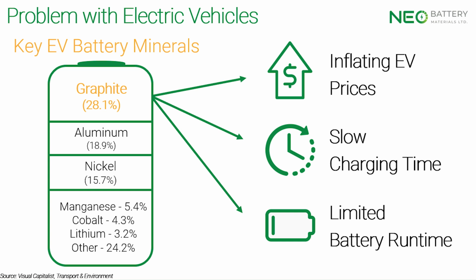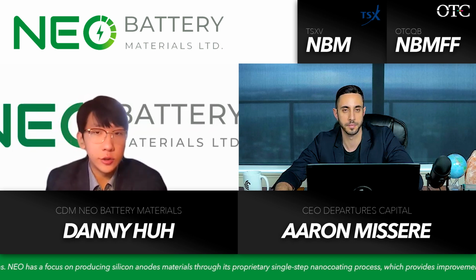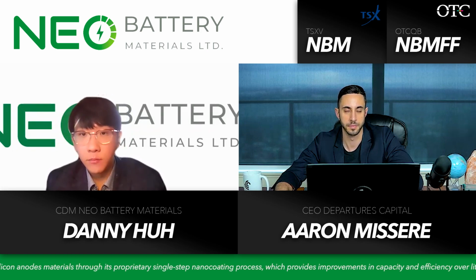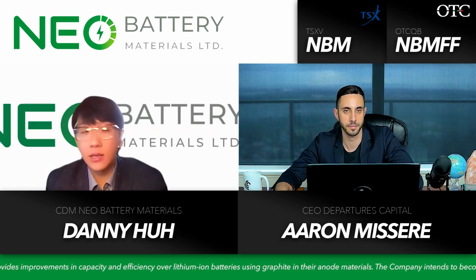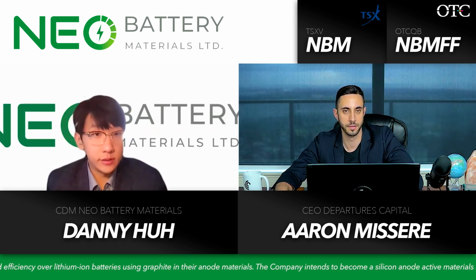And because graphite is the largest component of the lithium-ion battery in terms of weight, it contributes to the inflating battery prices today. And the reason why silicon is such a hot topic in the battery industry today is because it's recognized as a catch-all solution for graphite. So not only can it solve all the problems that I've listed, it theoretically stores 9 to 10 times more capacity than graphite itself. And if it's processed right, it can enable an ultra-fast charging characteristic. So this is why the industry wants to use silicon.